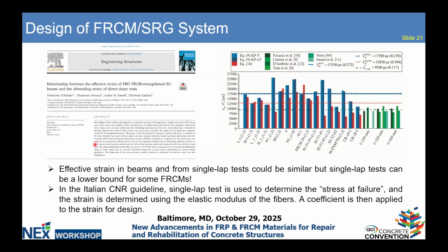This is where we need to do some research for 549. In FRP, the strain over a single lap can easily be 3 times less than the strain in the beam when you do design, because of the effect of the curvature and the presence of multiple cracks. In FRCM, you can go from 1 to 1.5 the strain on a single lap, and that depends on each single material. So we cannot use a single coefficient. The issue is that when we did this analysis of the database, there were not that many beams 7 years ago. Now there is more material, and we probably should test even more of these.